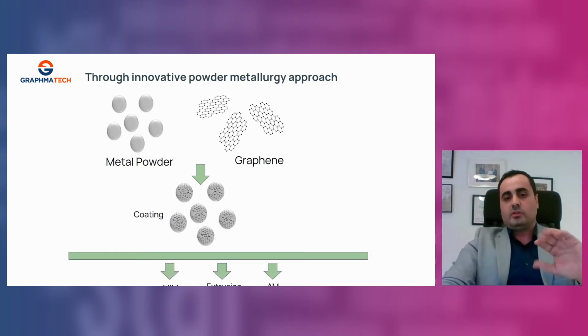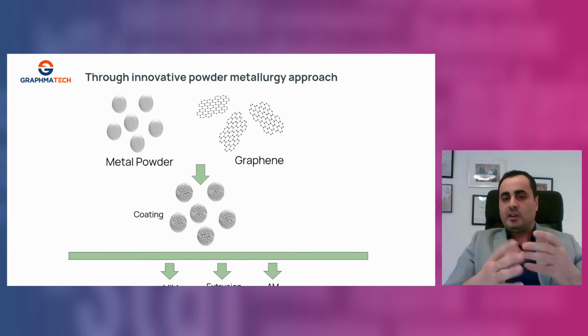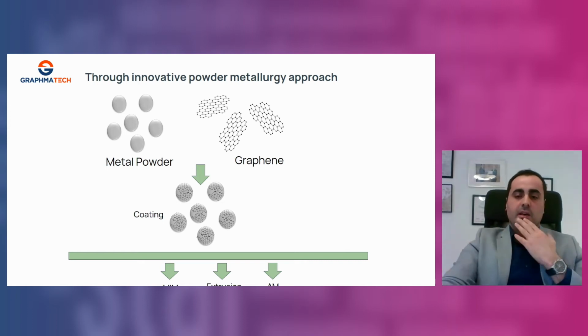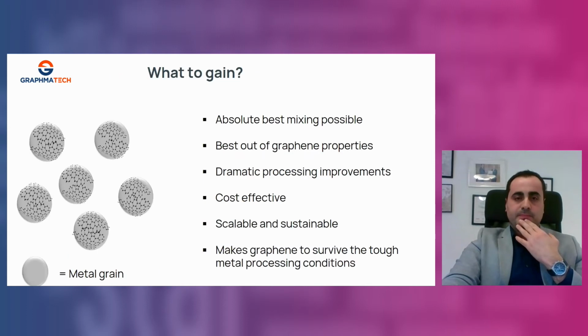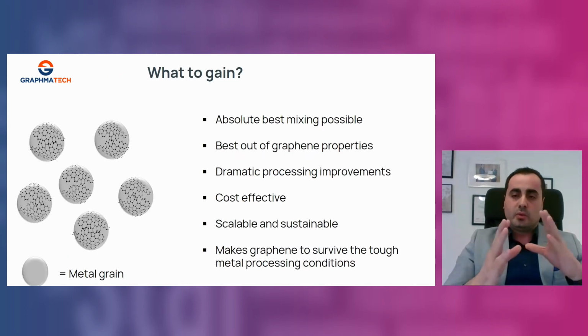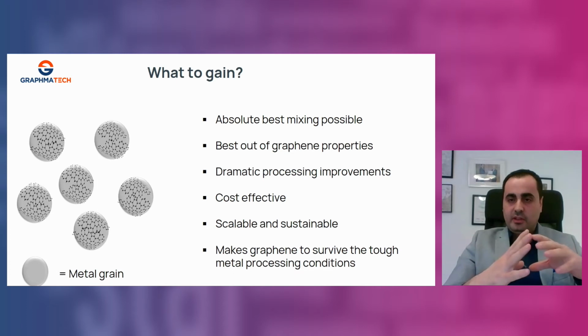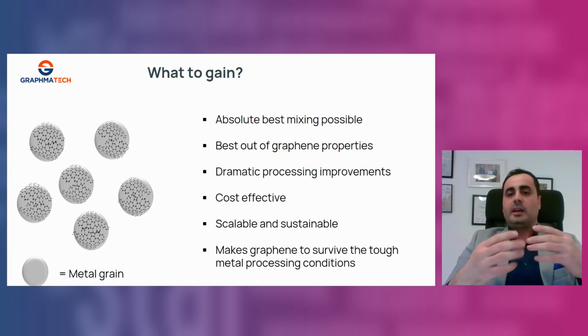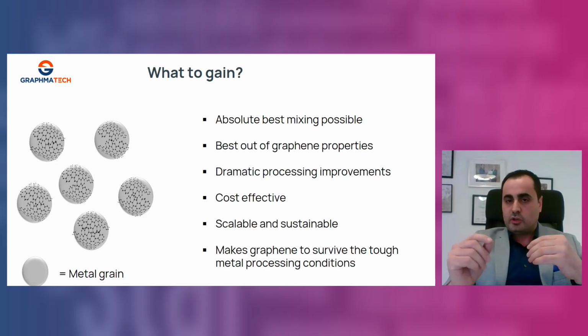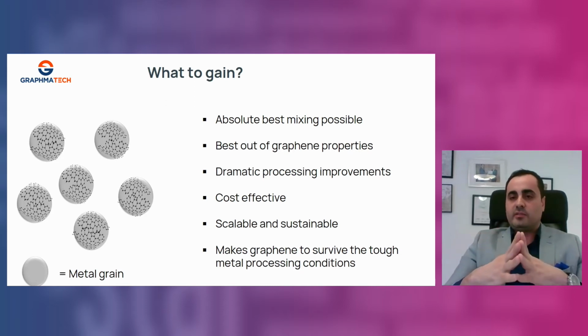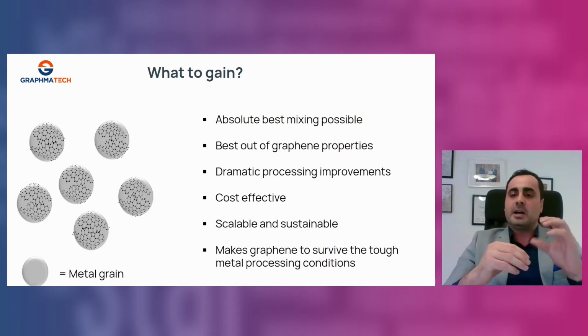After that, you take the next step. It can be injection molding, or 3D printing, or extrusion, you name it, or different metallic processing steps. By doing this, we have been getting the absolute best dispersion, because we guarantee that every individual grain has access to graphene in the way we want, and the concentration and the thickness we can control. And then, of course, we can make it cost effective. We use the minimum possible for getting the anticipated effect.